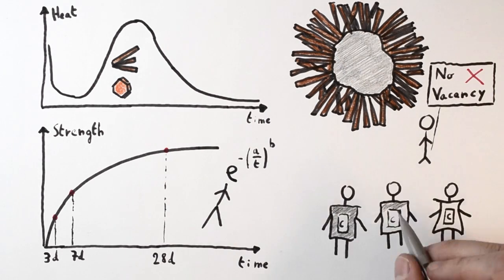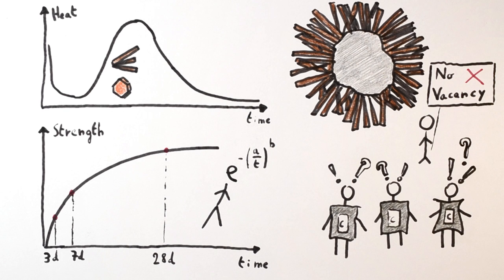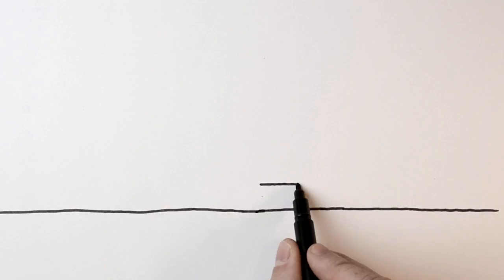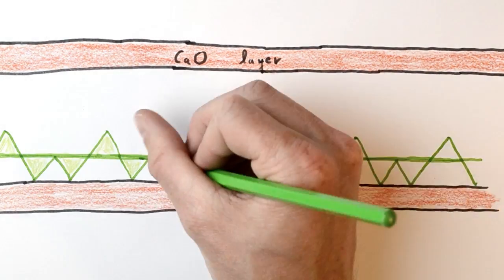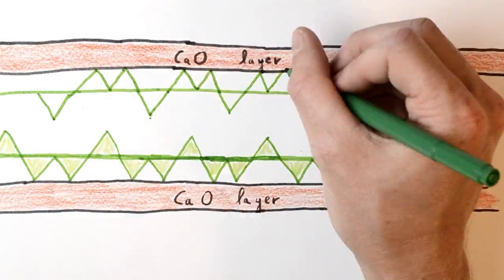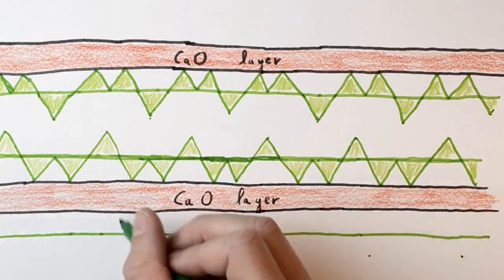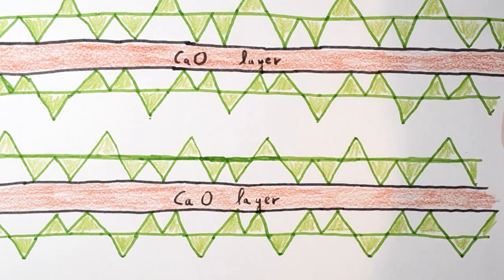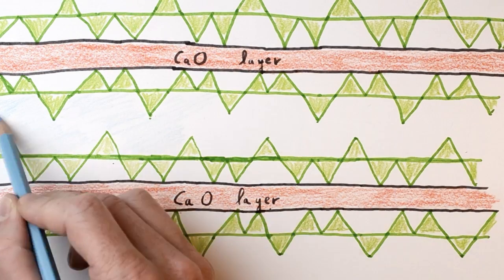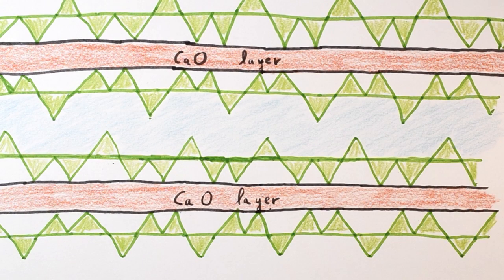The exact atomic structure inside the needles is still the subject of debate between cement scientists. It does not show a well-defined crystal structure, but rather a nano-crystalline region where short-range order exists. The features are somehow similar to the 14-angstrom Tobermorite mineral made of calcium oxide backbone layers, flanked by silicate tetrahedra on both sides, and containing significant amounts of water in the interlayer regions.